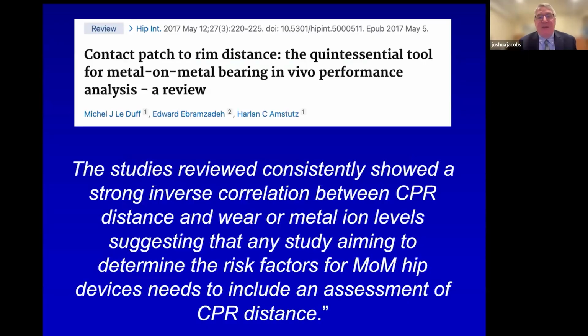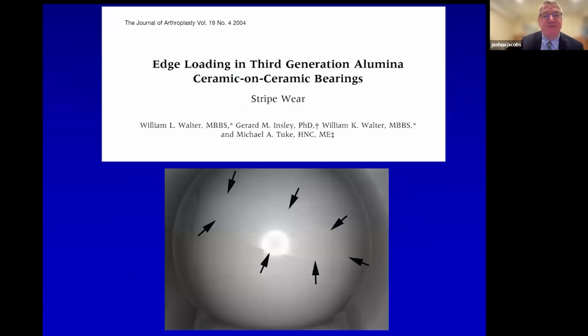In fact, this contact patch to rim distance is really a critical factor to understanding the individual performance of the device, as pointed out by one of the pioneers in the field, Dr. Harlan Amstutz. But edge loading is not just an issue with metal-on-metal bearings. It turns out that it's an issue with any hard-on-hard bearings in hip replacement.